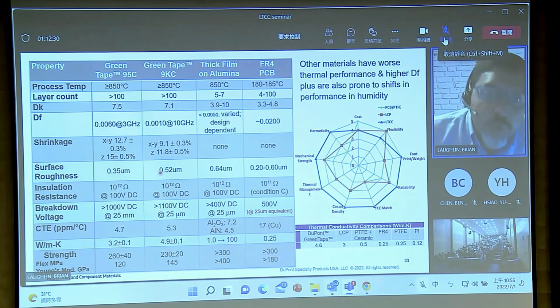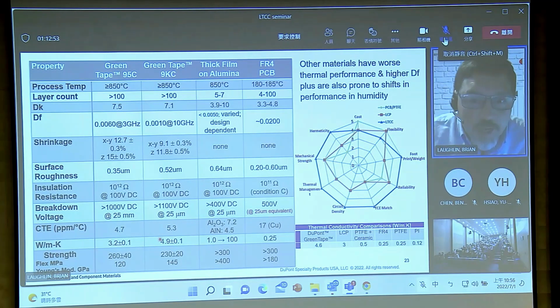Surface roughness is quite important. Once you get to high frequency, skin depth causes conductors to look more resistive than they really are at DC. So we're still in the sub-micron range of ceramic surface roughness. And then even the conductors inside usually either take on the surface roughness or might be slightly better through the lamination step. And the same goes for the thermal properties that we showed before.